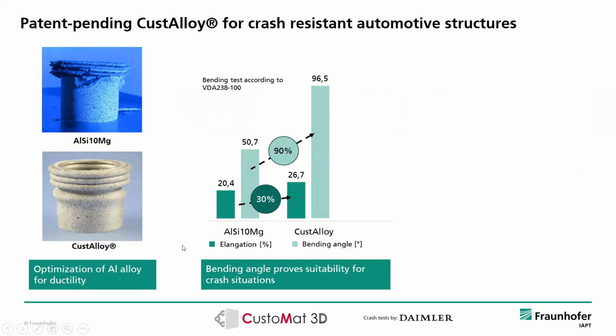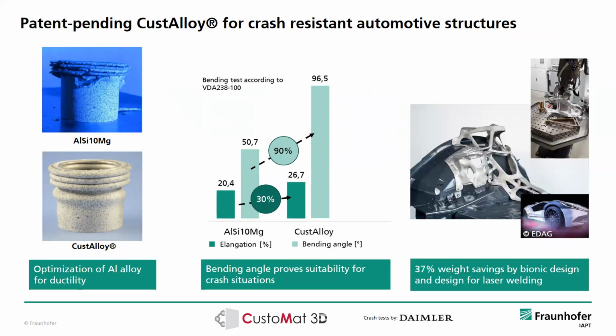And in terms of technology characteristics, we see that the elongation of the material is about 30% higher, increasing from 20 to 26%. But most important, the bending angle is increasing from 50 to 96.5 degrees, which makes for this really folding behavior of the alloy. Now we have transferred this material to our application demonstrator, which you can see here. It was built in 2 parts, and it was then laser welded together. And all together, with the design of these parts, we were able to save up to 37% in weight, and it was also tested in the EDAG concept car.